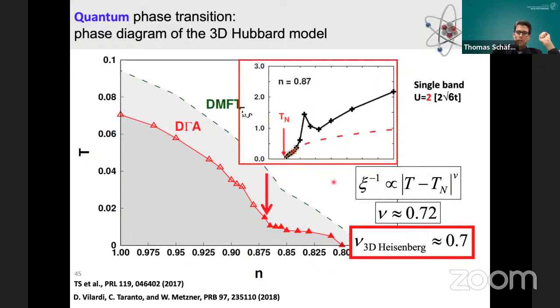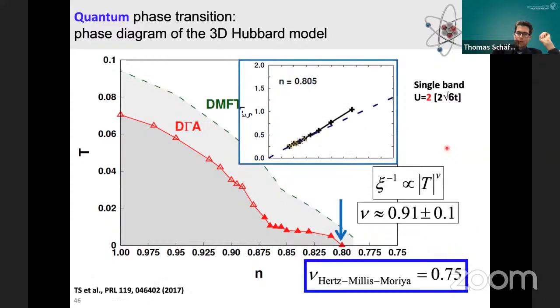This stays also true for larger doping, going to this incommensurate phase at low temperatures. However, if we go to the quantum phase transition and extract this critical exponent, within our numerical error bars we get an exponent of 0.91 plus minus 0.1, which is not in the Hertz-Millis-Moriya universality class. So what is going on here?